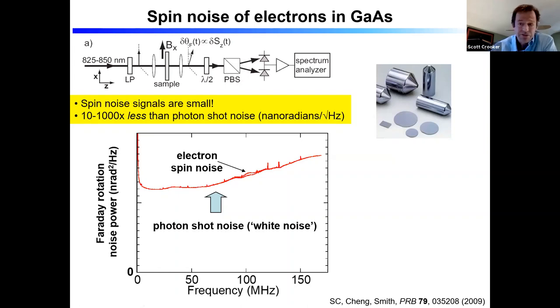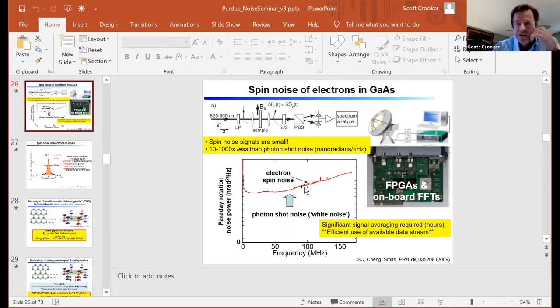For atomic systems where you've got nice sharp resonances and we can tune the laser really close to that resonance, it's very, very sensitive. We can be sensitive to just a few spins. In a semiconductor system, particularly if we focus down very tightly and are looking at a single quantum dot with a sharp transition, we're sensitive to single spins. In semiconductors and magnetic systems like ferromagnets and spin liquids, that sensitivity is much weaker because spectral features are broad. So one would have to back out that equivalence on a case-by-case basis. It can be done, but it depends on the dielectric function of the material itself.